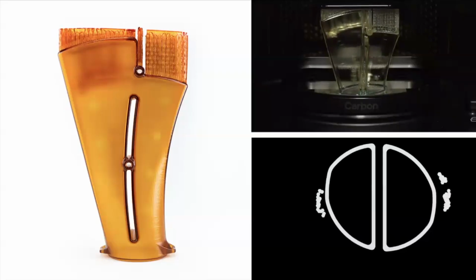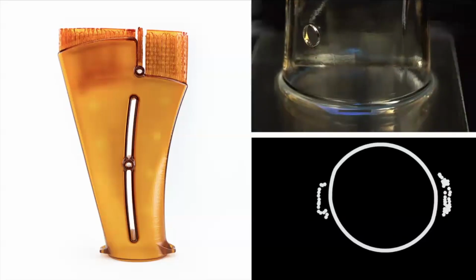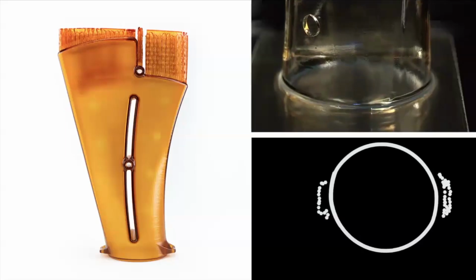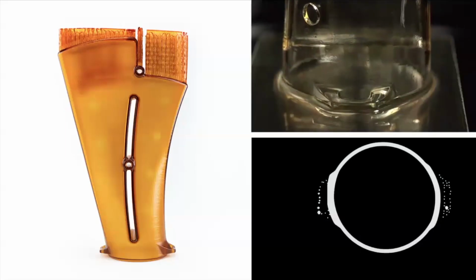And this allows the printer to go 100 to 1,000 times faster than a traditional 3D printer. Most 3D printers, it would glue to the window. Then you have to fracture it off the window to create a gap to bring in more resin. So this is a mechanism for resin renewal at the interface of the part.